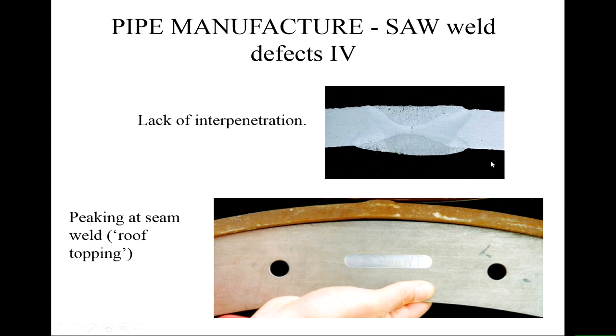This is the sort of thing, if it happens, that causes a burst during the expansion process or during the hydro test. It's one of the big causes. And it usually means that somebody's set the power settings incorrectly in the submerged arc system, so that we get incomplete penetration.